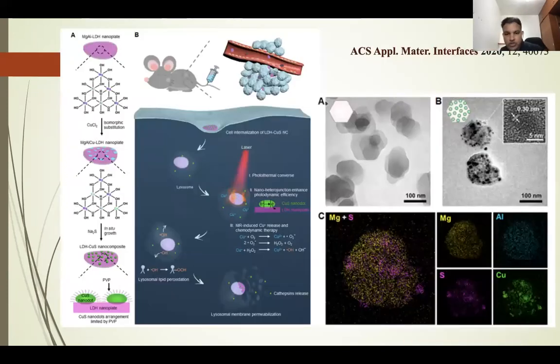And in another case, we use the surface chemistry of this layered double hydroxide nanoparticles, and we try to coat nanoparticles on the surface of this by using isomorphic substitution. So in this case, as I said, the material is based on divalent and trivalent metals. In that, the divalent is pulled out and replaced with another. For example, in this case, we used copper to replace. And after replacing, we try to